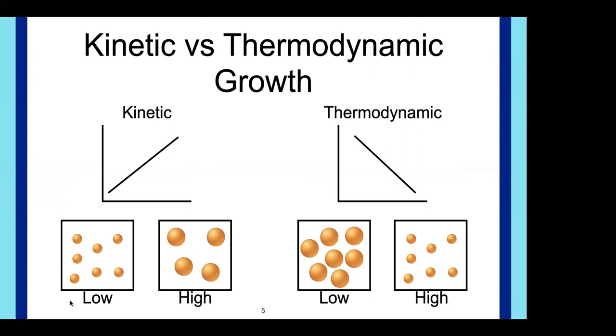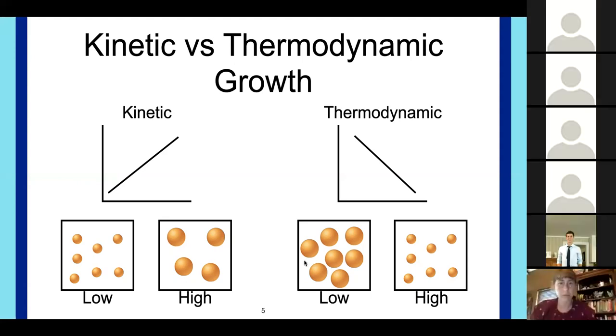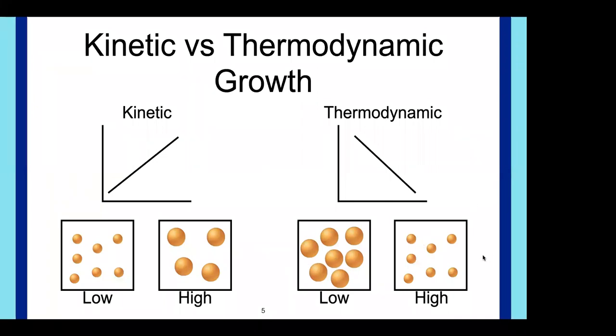Conversely, with larger timescale experimentation, you can access thermodynamic ranges. What we're looking at here is just stable size based on long-term solubility or stability in solution. At lower temperatures, you have lower solubility over time, so your supercluster assembly should grow larger. At higher temperature, you have higher solubility, so your supercluster should be smaller with more monomer units still in solution and not agglomerating.